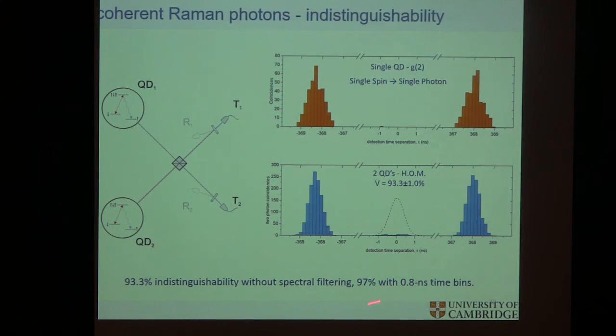What is interesting, and I wanted to highlight it here, not to say we can be better, but only to say that if we do a time filter, think of the wave packet coming out. These are shaped pulses driving this transition to scatter these photons. As I said, the quality of the photons is dictated by the quality of the ground state coherence. It turns out that if we slice off the last bit, the remaining tail of the photons, the quality goes up. So you see that the time evolution and the decoherence of the ground state maps itself onto the visibility coming from two independent quantum dots, because it's ultimately limited by T2. You can do spin echo to protect it. In these experiments, we don't, for the proof of principle.